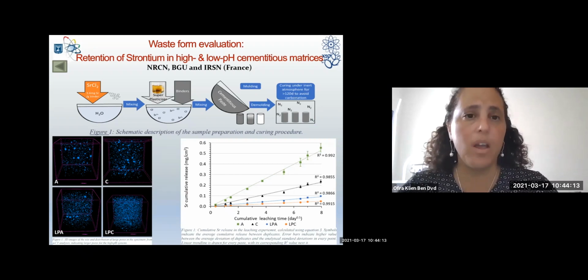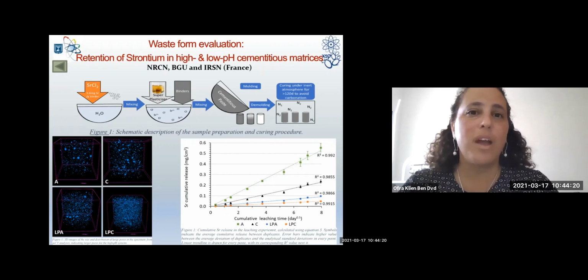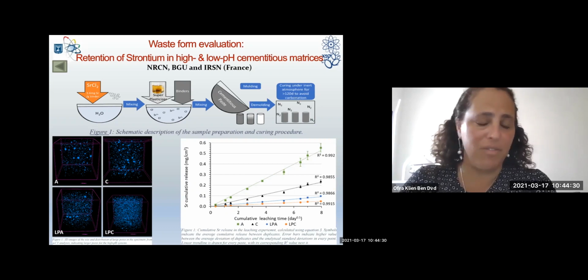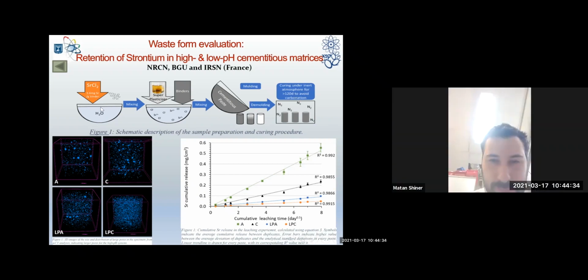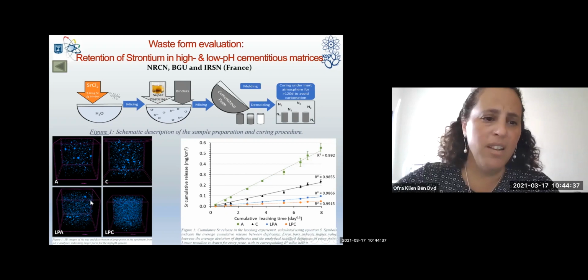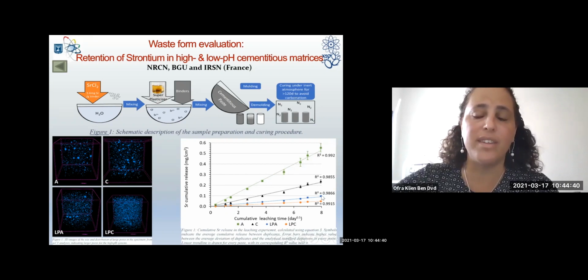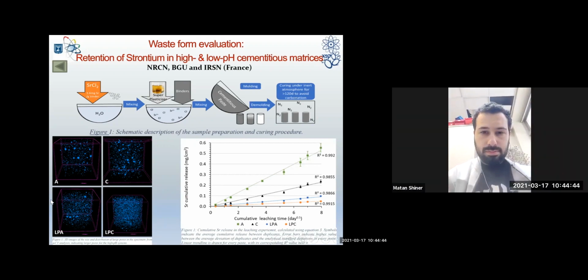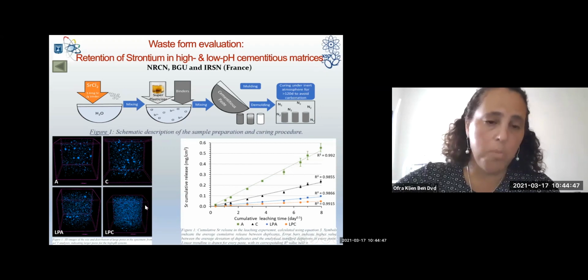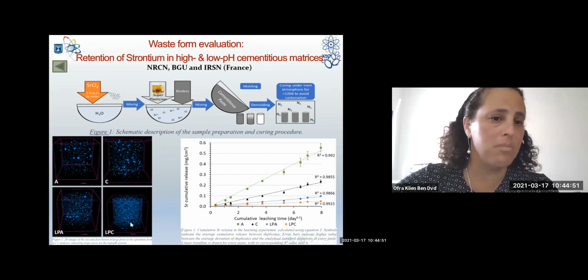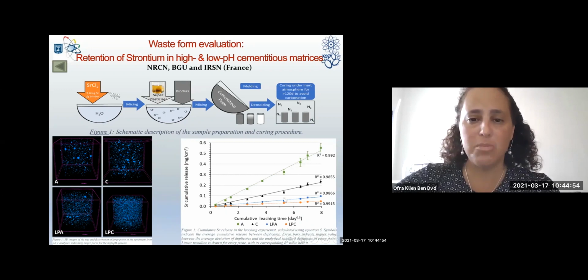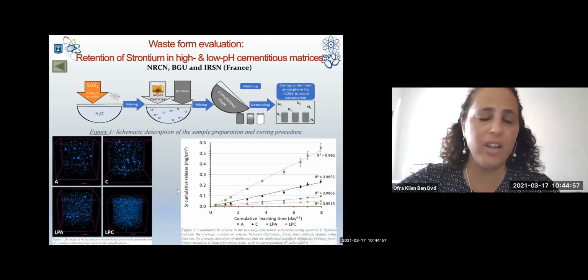So this is work done by my student, Martin Scheiner, who's here in the audience, I think, together with BGU University and the IRSN in France, where we dope cements with strontium, as I said, a very common radioactive material. We are working, of course, with a simulant, and we look at the leaching ability, at the retention ability of these matrices. And although the materials that have low pH have significantly higher porosity, both in the macro and the micro scale, they are much less leachable, and the waste is retained to a much better level than in the normal cementitious materials.